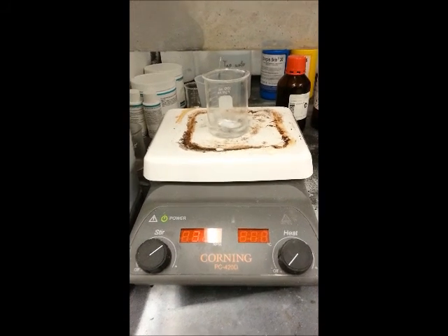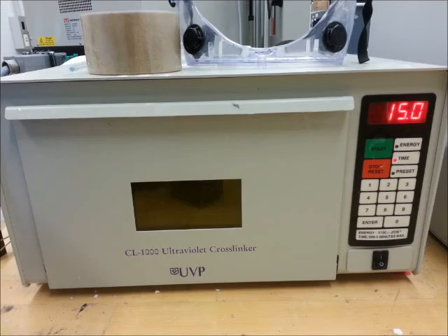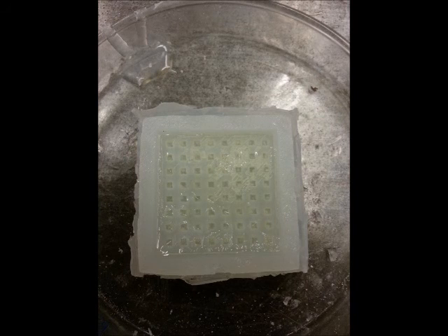Using Yakacki's method, I made SMP solution and swirled it for 5 minutes. Then UV cured for 15 minutes and heated it in the oven at 100 degrees Celsius for an hour. And here we have a hardened micro-pillar SMP.